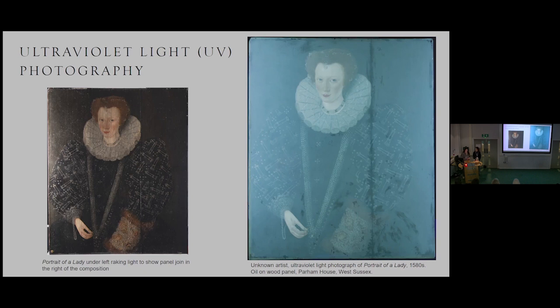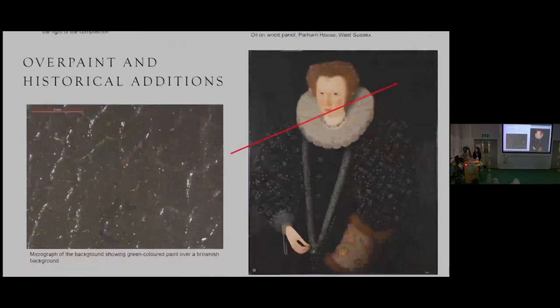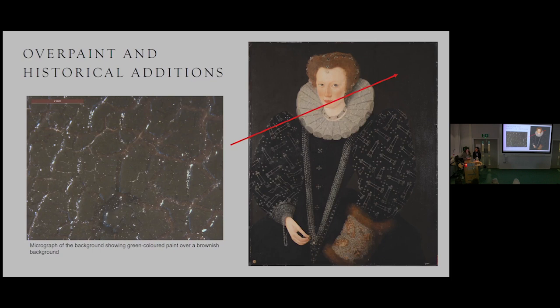For a painting of this age, it is not uncommon to have multiple campaigns of overpaint. Looking at the painting in ordinary light, the background has almost in its entirety been repainted. Large parts of the costume have also been covered. Many Tudor portraits do, however, have backgrounds that have been entirely repainted, as this was an easy task to do to cover losses or damaged paint, since they were usually painted in a single flat color. As we can see here in the micrograph, there's a dark green paint covering a more brownish background. So in between the paint cracks of the green, we see a more brownish reddish tone.